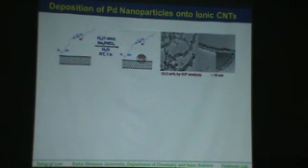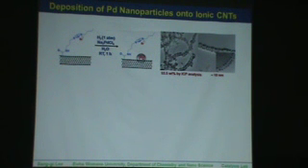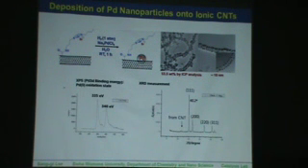The images show that the metal nanoparticles are well decorated onto the CNT surfaces, and ICP analysis indicated a maximum of over 50 weight percent palladium is deposited onto these CNTs. XPS analysis and XRD analysis clearly indicate these metal particles have good crystallinity.